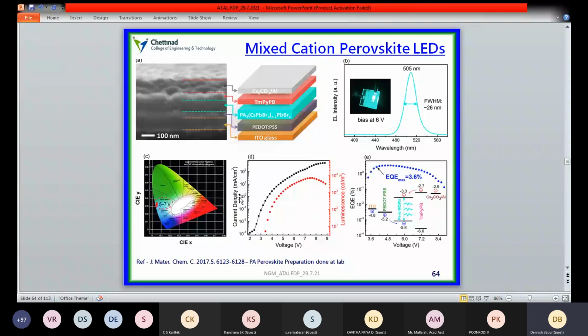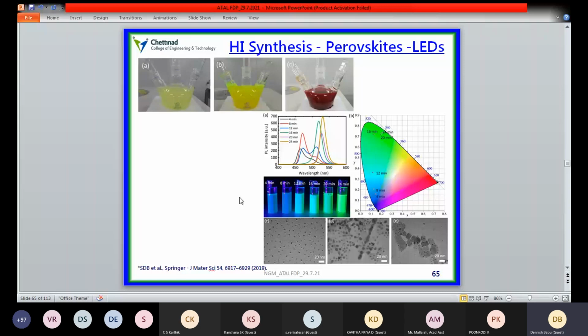We have prepared other perovskite-based systems with the hot injection method, and we have prepared different color variations, which you can identify with the CIE diagram as well as the UV lamp diagram. We varied the reaction time from 4 minutes to 20 minutes. If we increase the reaction time, the color changes from blue to green, and the size also changes from very fine nanoparticles to larger grain size particle structures. That's an important observation in this perovskite system fabricated in our laboratory with the help of hot injection synthesis.